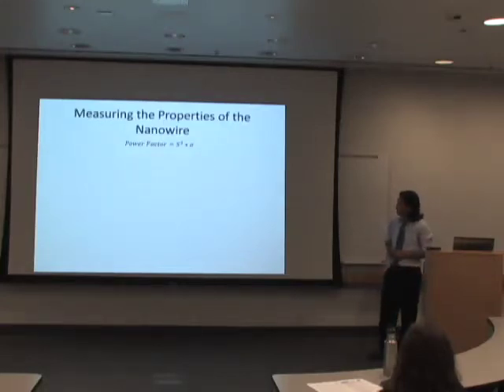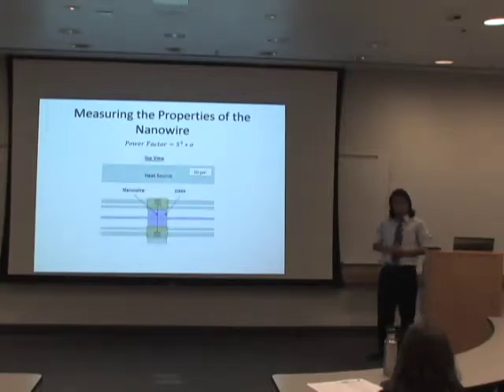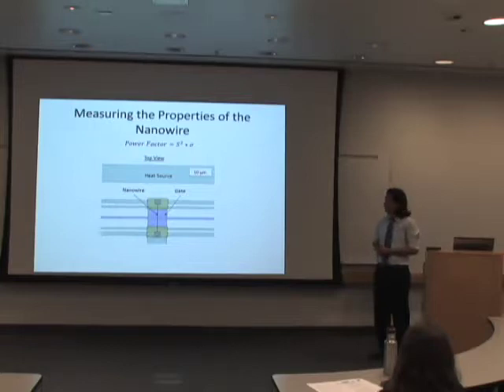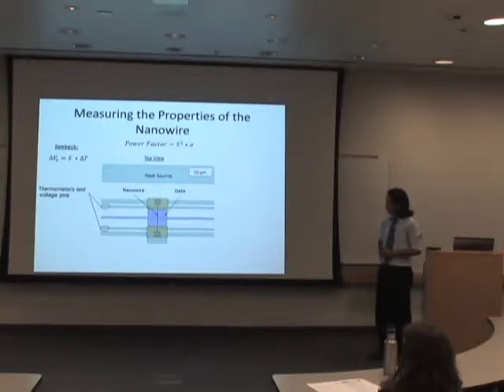Here are the parameters that we need to measure: Seebeck times electroconductivity. My mentor has worked on fabricating a device designed specifically to measure these two parameters. We have our Seebeck coefficient with this equation. As you see, we need to have a difference in temperature along the nanowire and measure the difference in voltage to calculate the Seebeck. So we have a heat source, which will heat up the nanowire to create a temperature gradient. And we have these electrodes, which will serve as thermometers to measure the difference in temperature and also to measure the difference in voltage.